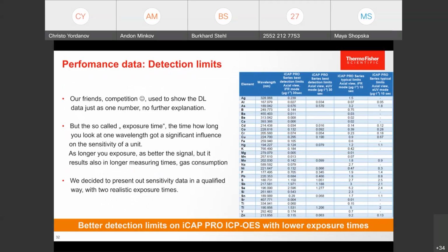In terms of sensitivity, this time we decided not to present a single number. We can say, aluminium, we are doing 0.027 micrograms per liter. That's it, full stop. But there is some background behind it. It's the so-called exposure time, meaning how long you look at one specific element. The longer you look at an element, the higher the sensitivity is. So with our new instrument we decided to present our sensitivity including different exposure times, 30 seconds and 10 seconds. 10 seconds is a quite usable and normal exposure time. So we have to say we are really good here. We also compared our numbers with the numbers of our friends, the competition, as long as they published them, and we are in very good shape, I have to say.